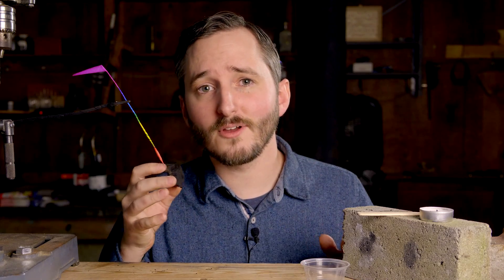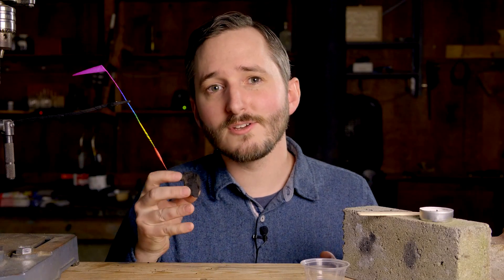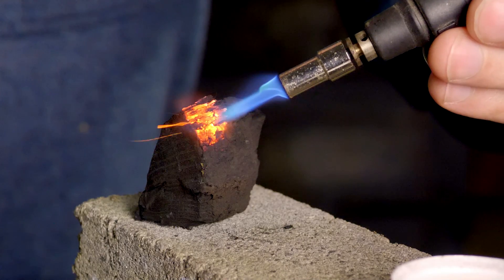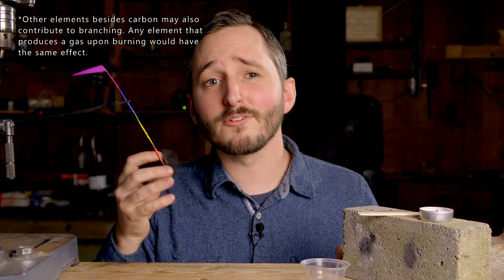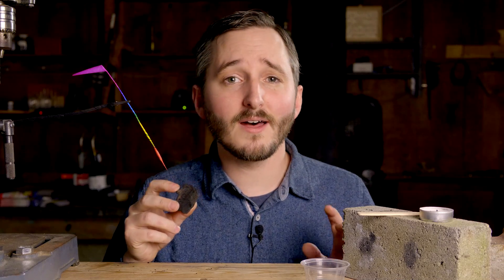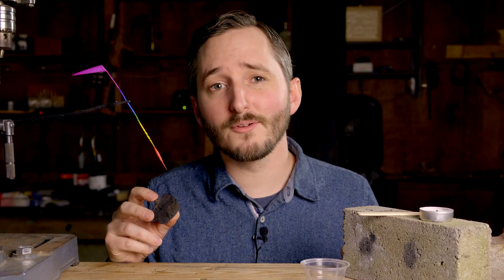Now, if you paid attention to the start of this video, you might have a new question. We've been talking about how carbon content in sparks causes them to branch, but earlier we looked at sparks from pure carbon and it barely branches at all — which is kind of weird. But this, I think, is a final piece of evidence that I've correctly identified the cause of branching sparks, which is the generation of gas bubbles inside a liquid drop. Carbon cannot possibly do this because it does not turn into a liquid when you heat it. Carbon sparks are solid, and so they can't form bubbles. Every once in a while you do see a carbon spark that splits in two, but I believe this is simply a fracturing of a solid object, like a rock splitting in half — not the same cause as branching in liquid sparks from burning metals or Senko Hanabi.